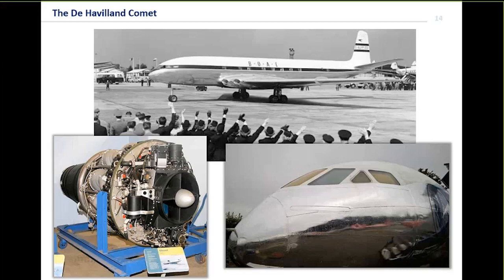Because weight was a premium as well, it used a really thin fuselage skin. It was 22 gauge, which for European people is 0.64 millimeters, so really thin for a stressed skin fuselage. And the reason it wasn't painted wasn't to make it look pretty, although it did look pretty. It was actually because the paint would have weighed too much, and therefore they couldn't have carried as many passengers. Later on, you see that the engines were changed to the Rolls-Royce Avon engine. But actually, they weren't in production until 1950, a full year after the Comet officially launched.